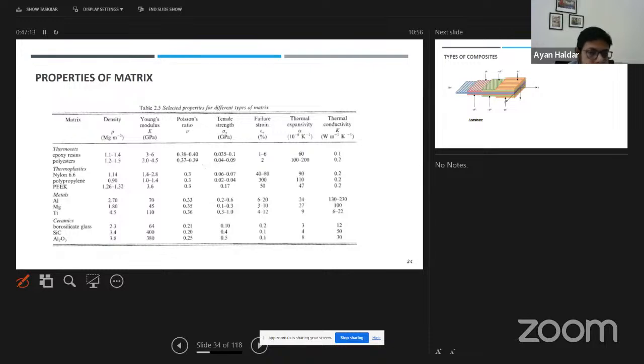And if you remember, the elastic modulus of carbon fiber was how much? It was about 200 gigapascal, right? Whereas if you look at the matrix, the thermosets have just got 3 gigapascal, or thermoplastics. So it's quite low. So with the polymer-based matrix, you can clearly see that your stiffness is offered only by the fiber and not much by the matrix, right? You clearly see how low it is. But on the other hand, if you see the percentage failure strain of some of these polymers, they are huge. That means your polymer can really undergo large strains. That means it can really deform to a great extent, right? That helps a lot in different applications where you really need these large deformations.